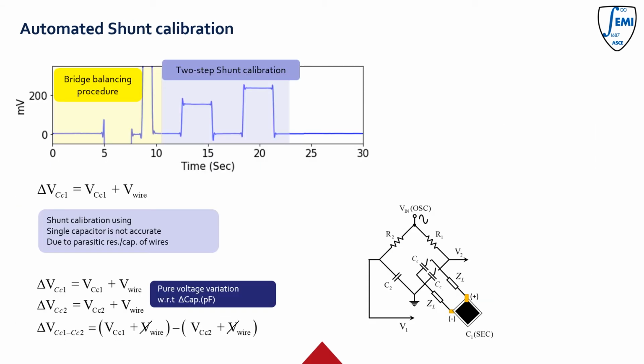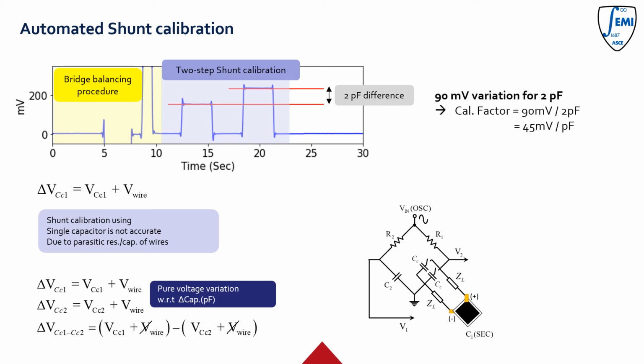For accurate capacitive strain sensing, the two-step shunt calibration was developed to eliminate the parasitic capacitance effect of the wire. The figure shows a sample measurement output of the bridge balancing and two-step shunt calibration procedure. Shunt capacitors were set up as 1 picofarad and 3 picofarad to make a 2 picofarad difference, and the two peaks around 10 to 25 seconds show the voltage variation accordingly. With the current setup, we found the calibration factor as 45 mV per picofarad.